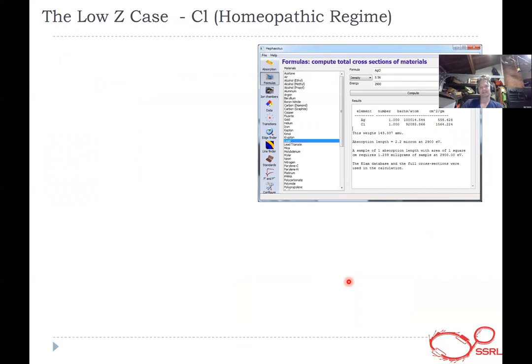So for the low Z K edges, like chlorine, I call it the homeopathic regime, where you want the idea of some sample in there. When you do the same calculation for chlorine and silver chloride, and the only number different is the edge energy, you can see that now your absorption length is 2.2 microns. So you may not get small enough particles to do this experiment. Sieving won't get you enough. There are techniques called raising the fines, and a number of different techniques you can look into. Talk to your beamline scientist to make sure you get small particle sizes. And one absorption length here, if you're going to do a transmission experiment, is 1.2 milligrams. So a very, very small amount.